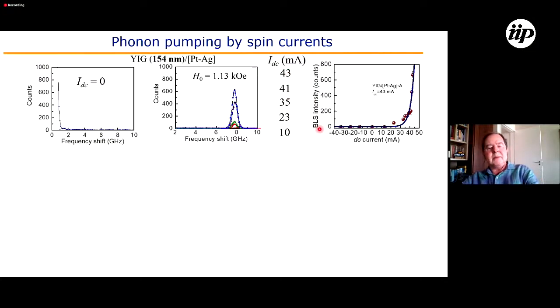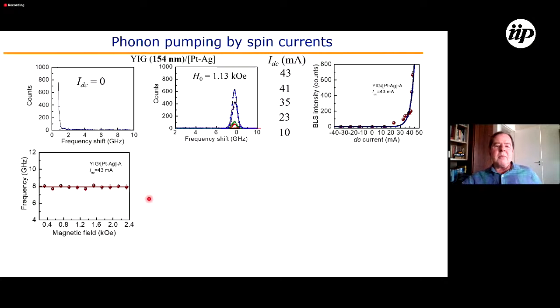We plot the intensity of the scattering, and this is the result. There is no peak until the current approaches some threshold, but then we measure the frequency of this pulse as a function of magnetic field. It does not vary with magnetic field.